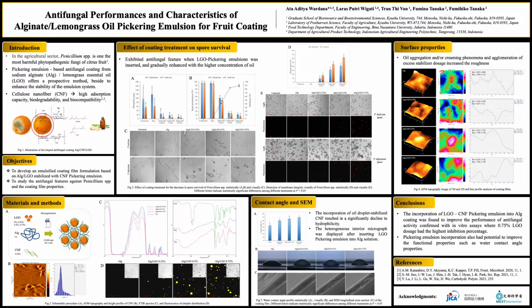Results also revealed that the incorporation of emulsion resulted in a significant decline in hydrophobicity measured as water contact angle, shown in figure 5A and B. SEM analysis revealed that the alginate thin coating film exhibited a compact, continuous, and homogeneous appearance, and no clear separation was found. However, a heterogeneous interior micrograph was displayed after inserting emulsion, and a more amorphous structure was easily observed at a higher proportion of oil.